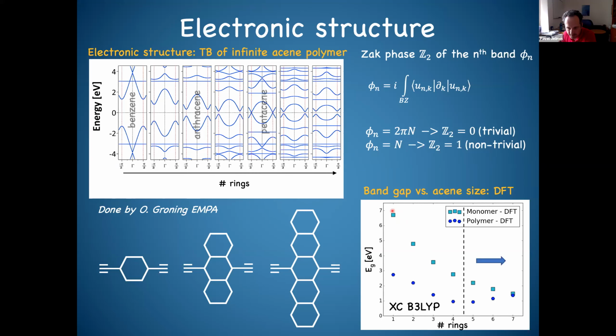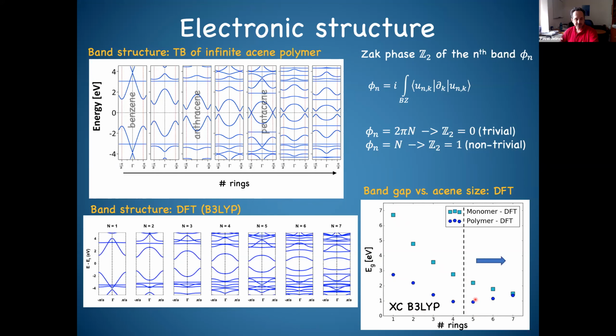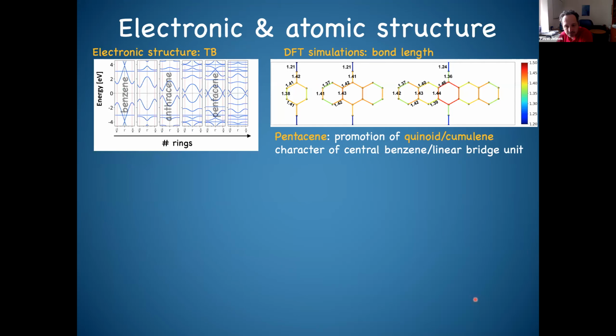So we have the acenes, the monomers, with a continuous decrease of the band gap. Now for the polymer, I do the same calculation, DFT with the hybrid B3LYP. I see a decrease of the band gap up to between 4 and 5, and then the band gap starts to open again. So it means that I have some transition here, between tetracene and pentacene. And again, this is the band structure calculated from DFT. Now I can also look at the optimized structure and the distances.